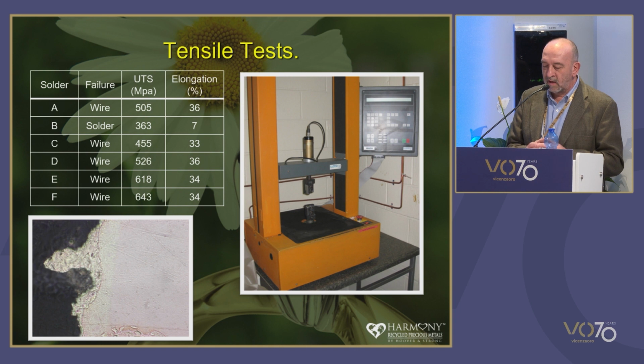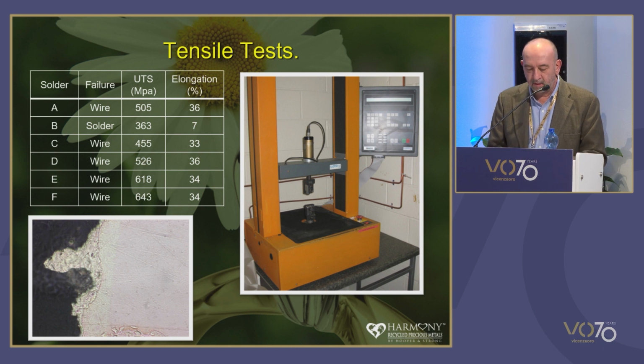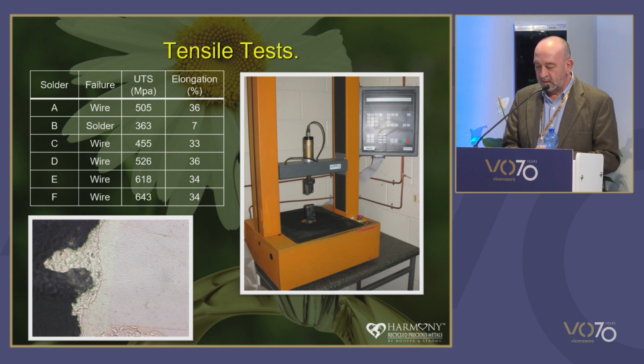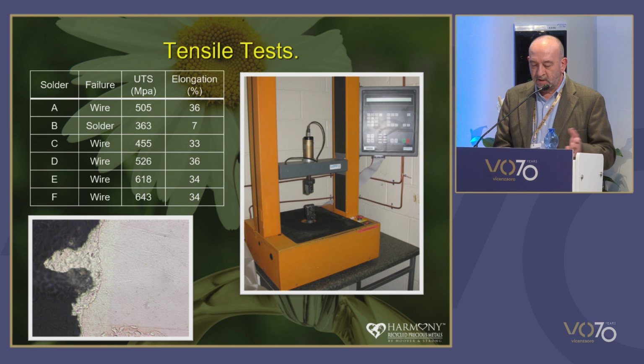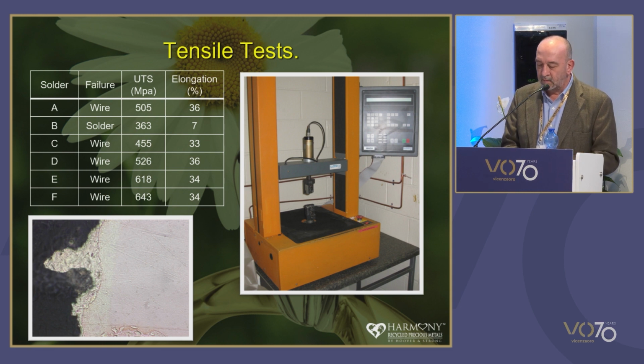Failure at the joint will either be because the parent metal solder bond is weak, or the solder itself is brittle and has low elongation. So we took 1 mm diameter wire, and we soldered them together using the torch method only for this test. It was a little bit difficult to do it in the furnace. And the results here show that only one sample failed at the solder joint, and it was again solder B. And looking at the marker section there on the left, we can see that the failure was through the solder and not at the interface, suggesting the mechanical properties of the solder were the problem here.